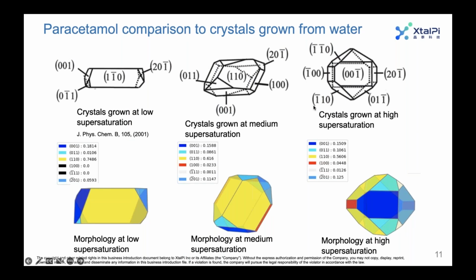There are systems that are very sensitive to the supersaturation, like paracetamol. Here I have three examples of paracetamol crystals grown in water with a low supersaturation, a medium supersaturation, and a high supersaturation. We used our in-house model for this, which is an ECM-based method, or Einstein crystal-based method. And it's able to capture some of these morphological changes.